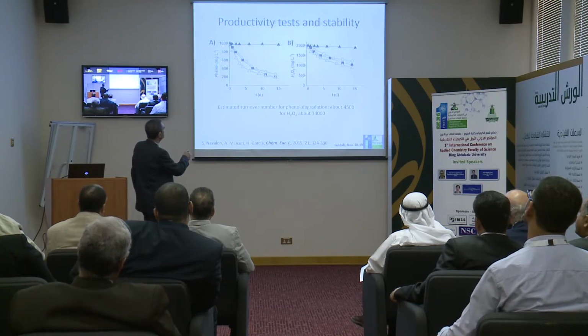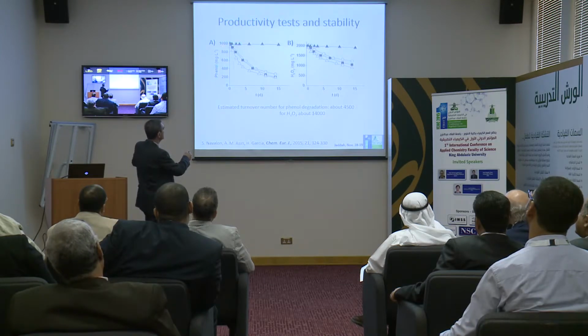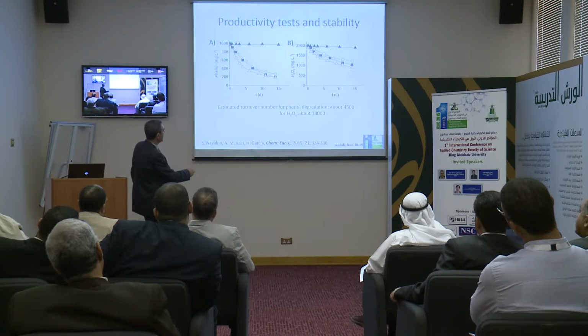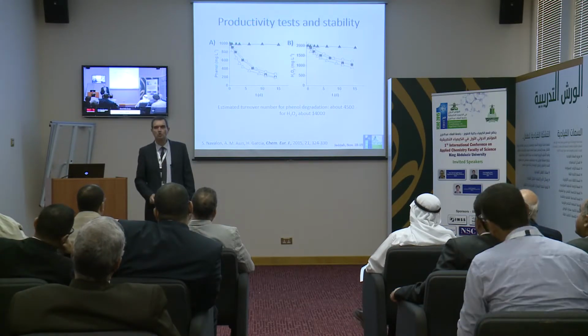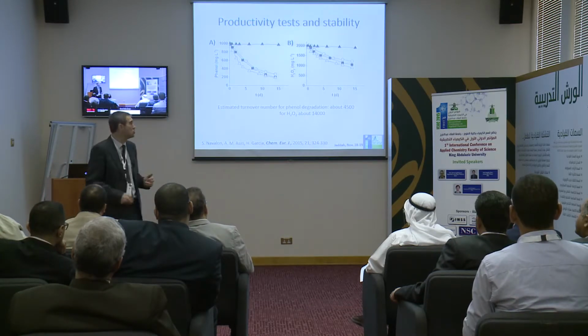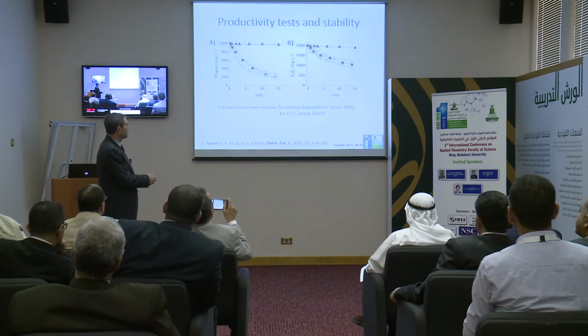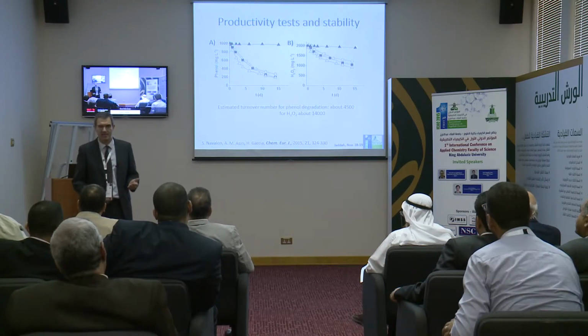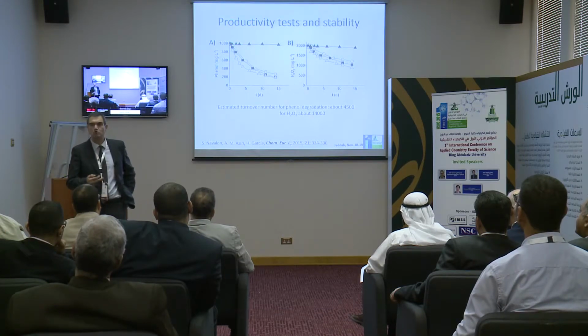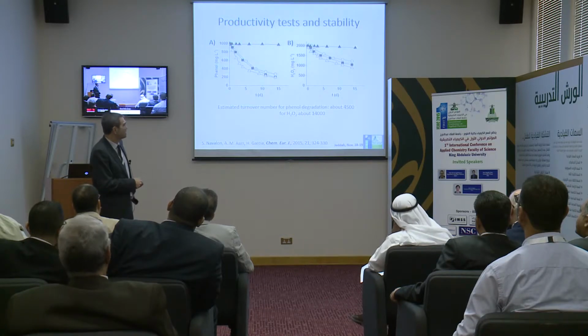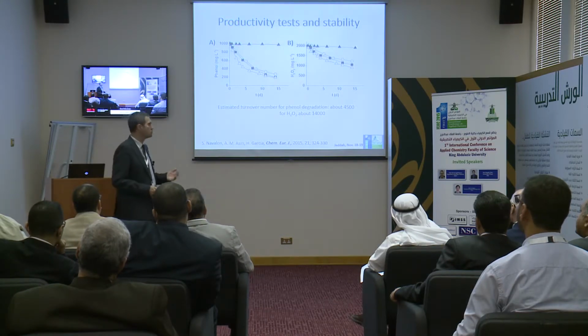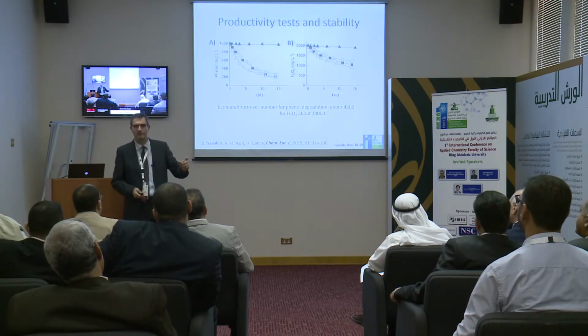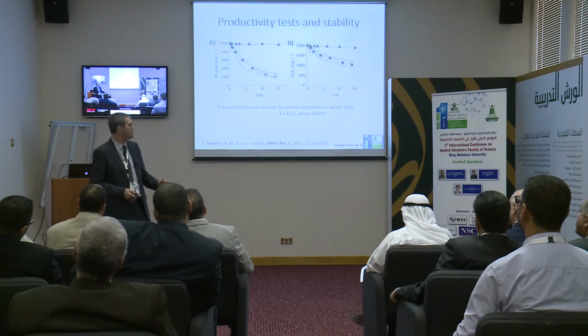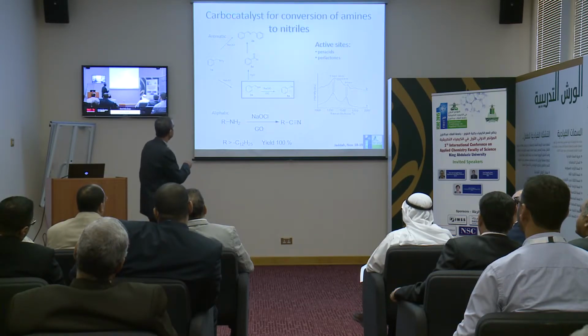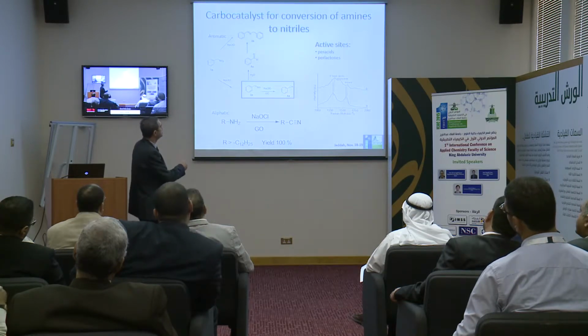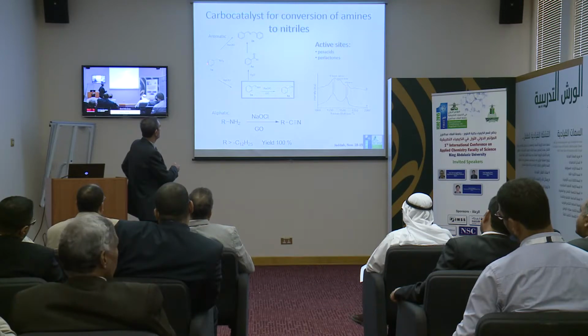Productivity, notice this scale. This scale is one order of magnitude larger than before. So we can degrade a lot of phenol, and actually we have determined the turnover. The turnover number, considering that our sites are oxygenated functions, is 4,500 for degradation of phenol. That is not very high compared to the state of the art. For metallic catalysts, the turnover is about 10,000 or so. So it's not the record, but we are very close to the catalytic activity of some metals. And probably our hope is to design a specific graphene that contains a higher density of sites and to increase the turnover. Graphenes can also be carbocatalysts for the oxidation of amines to nitriles. So this is one reaction going from here to this.